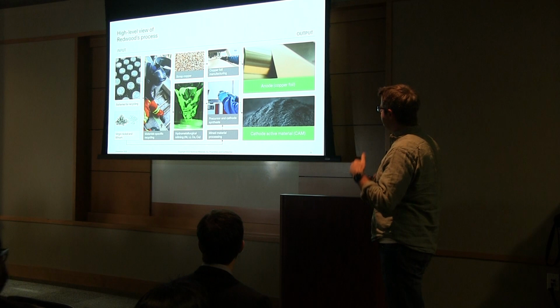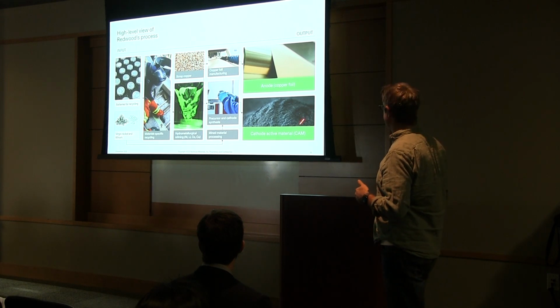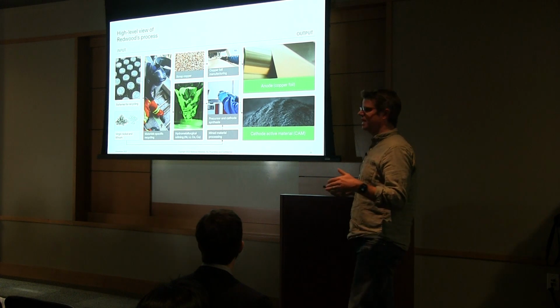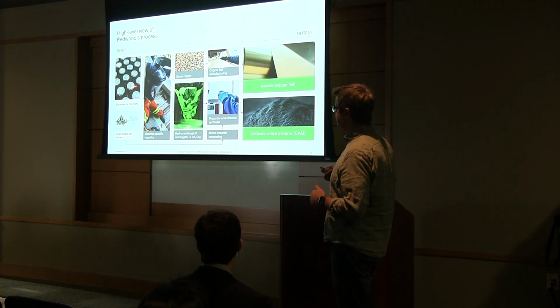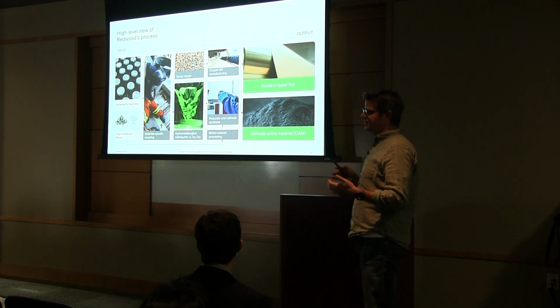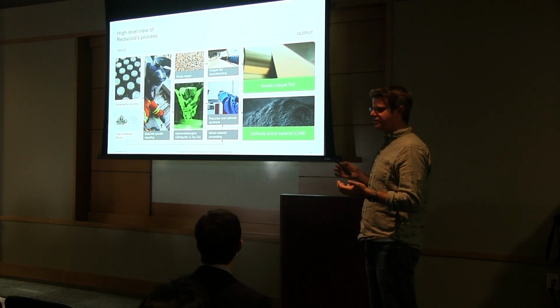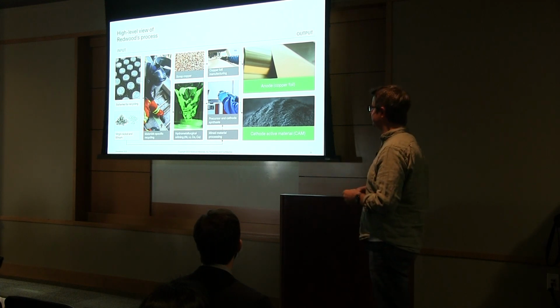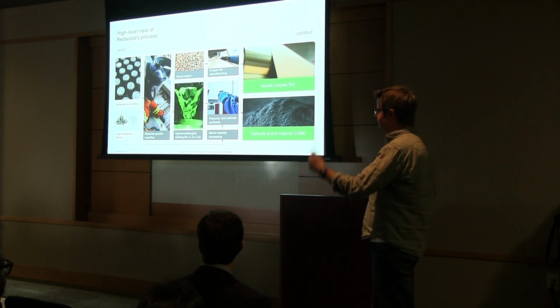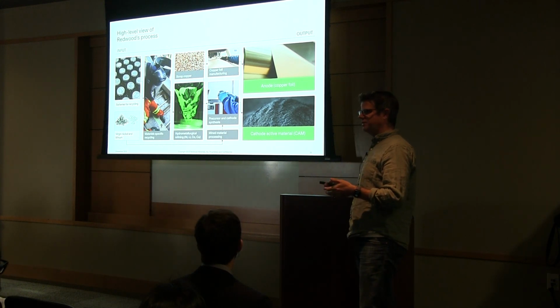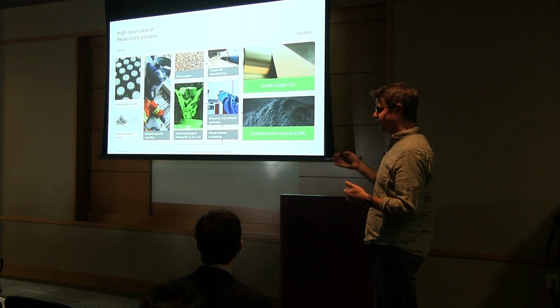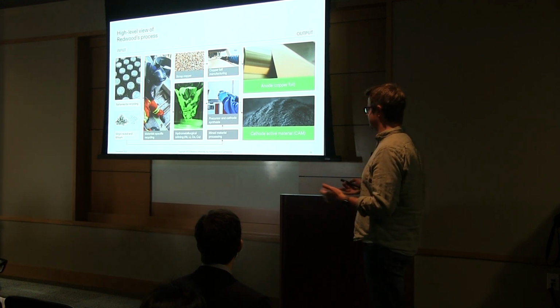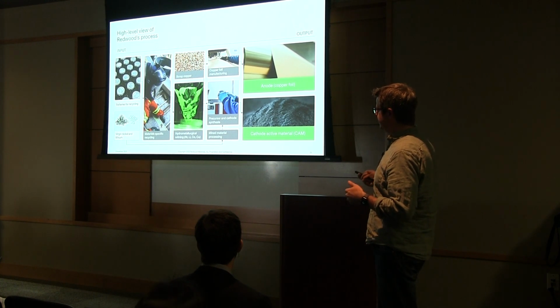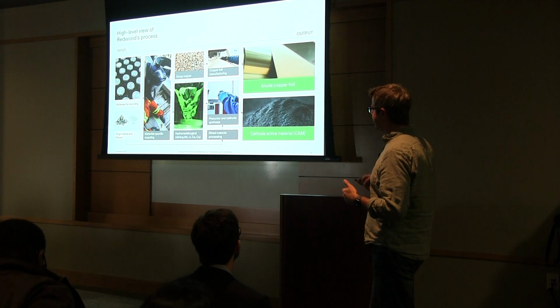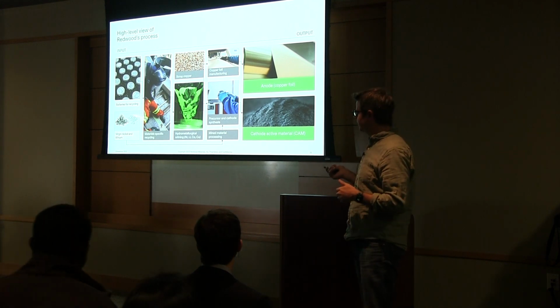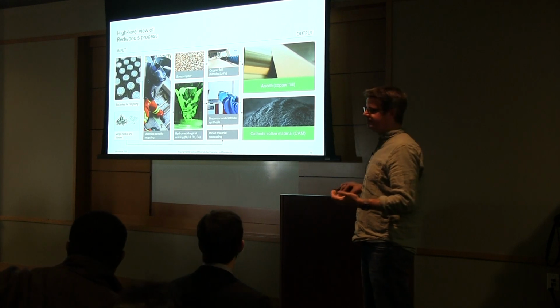When you're attempting to produce anode copper and cathode active material at the quantities that we're looking at, this can't be met with recycling alone. So approximately 20% of the metals that go in will be from recycled sources. That will vary from customer to customer. Some will be higher. Interestingly, a lot of cell phone and laptop batteries are a high cobalt chemistry, meaning that we can largely meet cobalt demands from recycled batteries, which is great considering where mined cobalt typically comes from, something we want to reduce and avoid if possible. But the balance in metals is met by what we call virgin nickel and lithium. That's mined nickel and lithium.